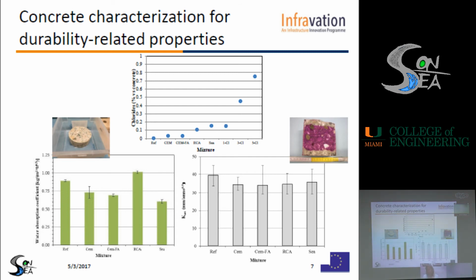On the right, we can observe the result of another test, which is the carbonation test. This is the accelerated carbonation coefficient, which gives an idea of the resistance to the penetration of the carbonation. We can observe that the presence of chloride in the mix didn't significantly affect the resistance to carbonation, since comparable results were obtained on all the different mixes.